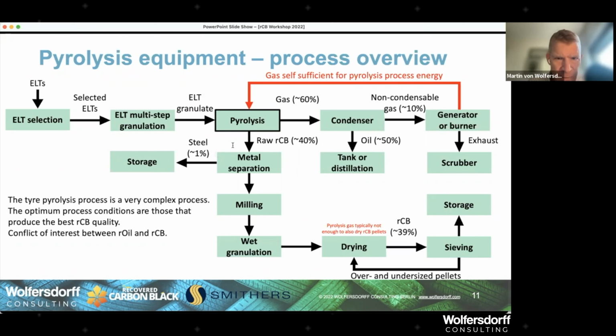Carl, why are the prices for steel different pre or post pyrolysis, and how much is the difference? Okay, I'm not a steel expert, but I would claim for recycled steel you get anything like $200 or maybe 200 euros if it is separated mechanically and not undergoing temperature treatment. Don't forget the pyrolysis is typically 500, 700 degrees, and that changes the structure of the steel.